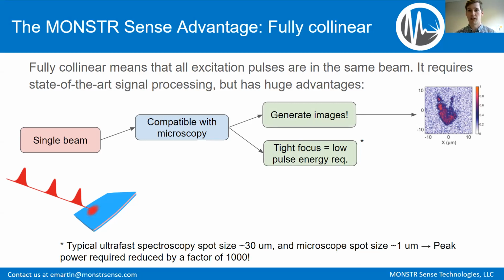Also, being compatible with microscopy means that you can focus the beam tightly, right? And this is great because this significantly reduces the pulse energy requirements. To give you a sense of scale, a typical ultrafast spectrometer is fundamentally limited to have a spot size of about 30 microns, whereas a spot size with your typical microscope 20x objective is focused down to 1 micron. And so what this means is that you have a peak power requirement that's reduced by a factor of 1,000 by shifting towards using microscopy.